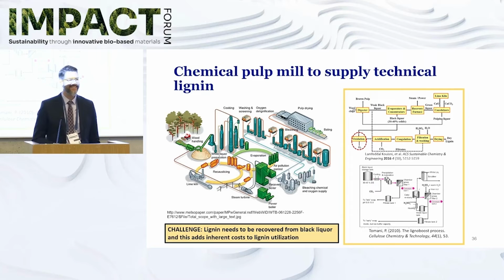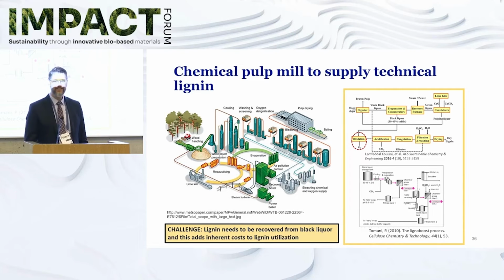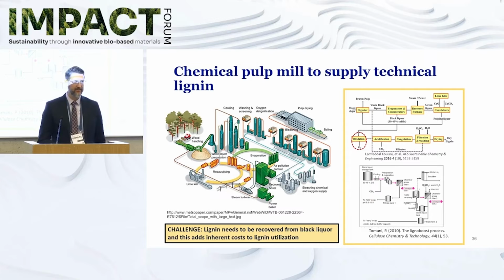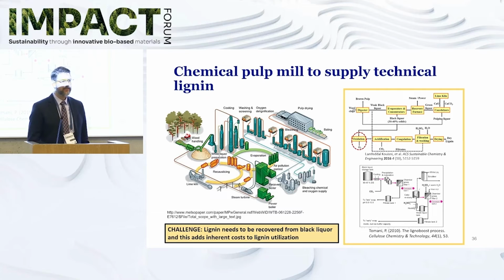And so the last presentation mentioned the use of lignin from the recovery boiler. And so we can pull some of that lignin out. And so if we do that, there's a couple processes that have been developed. One's the LignoForce process, one's the LignoBoost process. These have been developed in the really past decade or so, where you use CO2 in order to precipitate the lignin, and then there's different acid washing stages to kind of clean up the lignin. And so this is great.